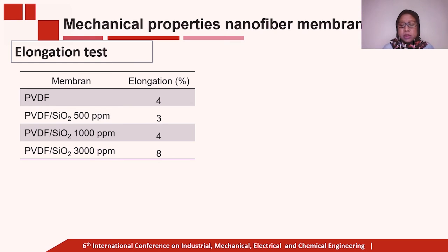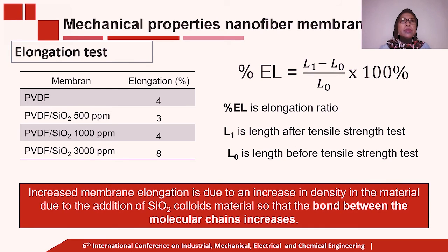And the second is elongation test. From this table, we can see that increased membrane elongation may be caused by an increase in the material density due to the addition of SiO2 colloidal material, so that the bond between the molecular chain increases.